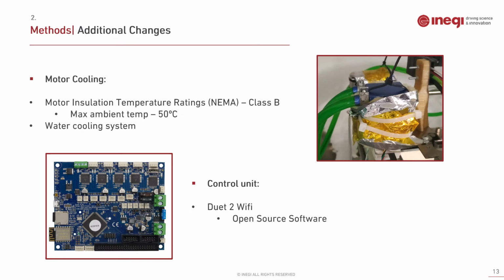The first, the motor cooling to try and keep the winding temperature below 130 Celsius degrees, which would mean try and replicate an ambient temperature of about 50 Celsius degrees. For this, we implemented a liquid cooling system like the ones used for computer processors. The liquid used for this purpose was ethylene glycol.